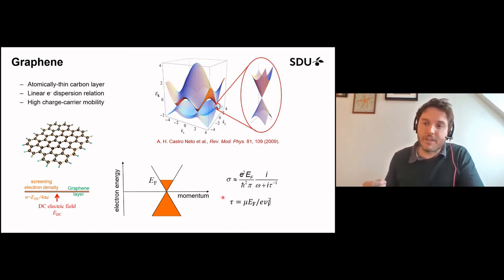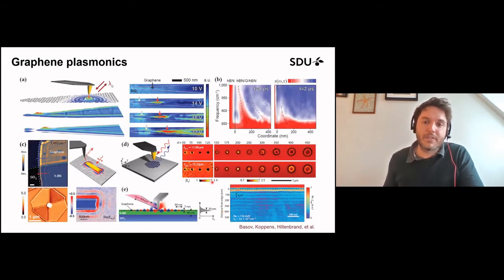And moreover, it's a high quality metal in the sense that it has relatively lower loss than gold and silver, let's say. So the two main points are addressed here in the fact that you can electrically tune the charge density, and therefore you can electrically tune the plasmon resonances, and also that the plasmon resonances seem to have a higher quality. So, as I said, there's been an explosion of research in this area, and here I've highlighted a number of experiments where the graphene plasmons have been imaged in real space using scanning near-field optical microscopy.